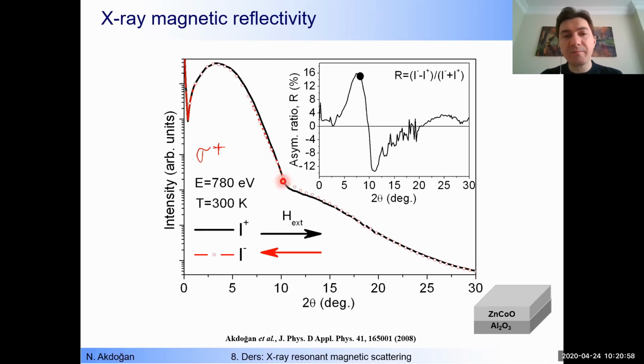But what about in reality? In order to see the real differences between the two curves, we have to plot the asymmetry ratio as a function of the 2 theta angle. This scale is the same, but the y scale is different now: asymmetry ratio. What is the asymmetry ratio? This is the asymmetry ratio R. Here we have intensity plus minus intensity minus over the total intensity given by intensity plus and intensity minus. Okay, this is the asymmetry ratio. If you plot the two curves in terms of asymmetry ratio, then you get that type of signal. What we have here is more or less no difference between the two curves. It is around zero, more or less zero around those angles, and zero around those angles. You can consider it like this.